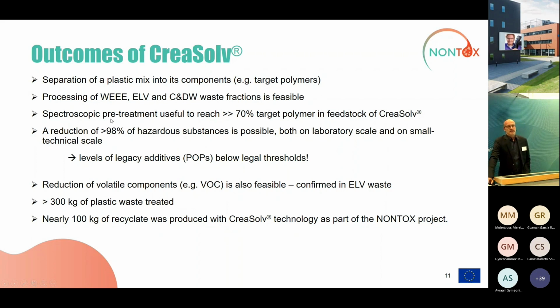We found out that it's useful to have a spectroscopic pre-treatment, which allows us to increase the target polymer in feedstocks for the CreaSolv process to levels of greater than 70%. Sometimes we were even in the range of higher than 90 or 95%, but this is not necessary. We like to have at least a bit higher target polymer concentrations. This is why we set this 70% target here. The spectroscopic sorting is better than 70%, but this is what we have as a minimum request to be more efficient in our processing.